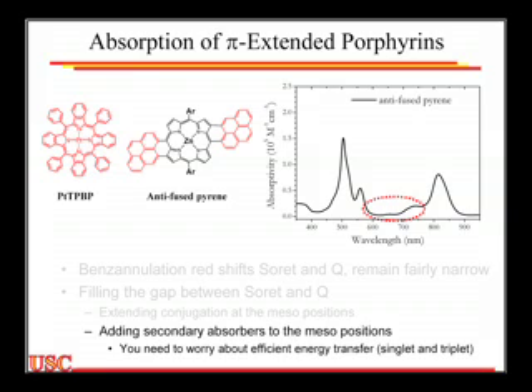So the thought was, if we absorb in tetracene, this is the singlet absorption, the fluorescence is right here, and it overlaps very nicely with the absorption of the porphyrin. It's perfect for Förster energy transfer. So this will make a great sensitizer for the porphyrin, because it'll fill this gap. Any energy we absorb here will transfer into the Q band of the porphyrin.